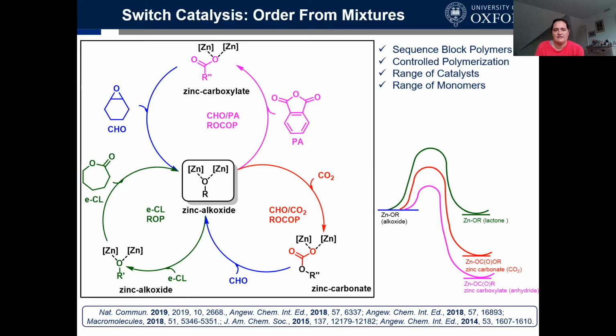How this works is that we essentially have a common intermediate to 3 catalytic cycles, and we dictate which cycle we're in by controlling the chemistry of the metal intermediate. Here you can see that the common intermediate is a zinc alkoxide. It could indeed be any metal alkoxide, but let's take zinc. By controlling whether we have a carboxylate, a carbonate, or an alkoxide formed, we control which cycle we're in. And we have discovered that from mixtures of monomers of these types, anhydrides tend to have both the lowest barrier to insertion in the transition state, but they also form the most stable linkage.